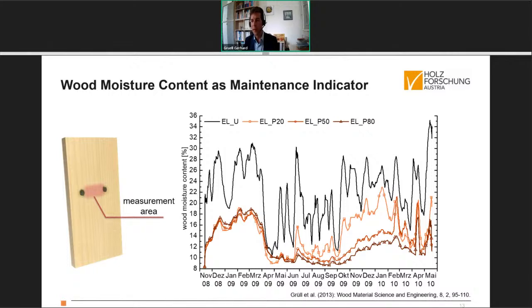The water-based system applied in 20, 50, and 80 micrometers dry film thickness. Here you see that over the first spring period, all coatings were in good shape and good conditions and protected the wood very nicely against moisture. So the moisture fluctuations were low, in particular compared to the uncoated wood again.